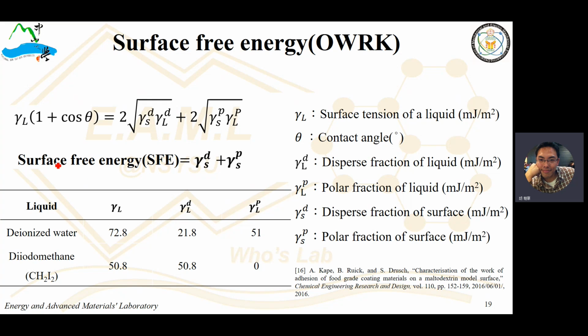Okay, so you can look at this and we measure the contact angle. And we use two types of liquid. One is water, which is the polar solution. And the other one is diiodomethane, which is the dispersive solution. Okay, therefore we can measure the contact angle of the surface, and use this table to find out the surface energy of these two types of liquid, polar and dispersive. And we can calculate the surface free energy.